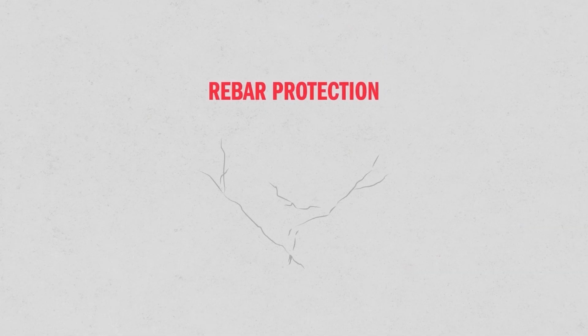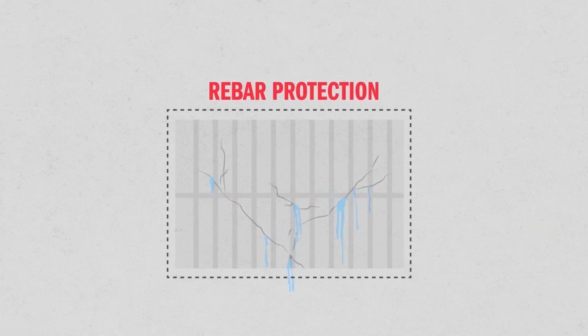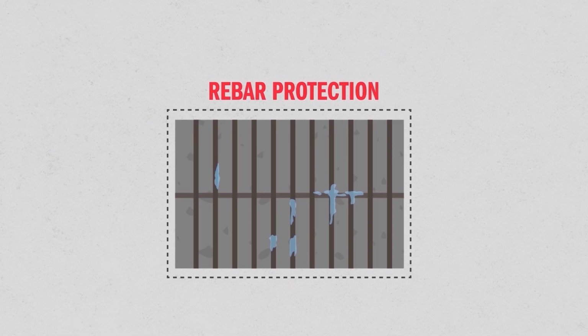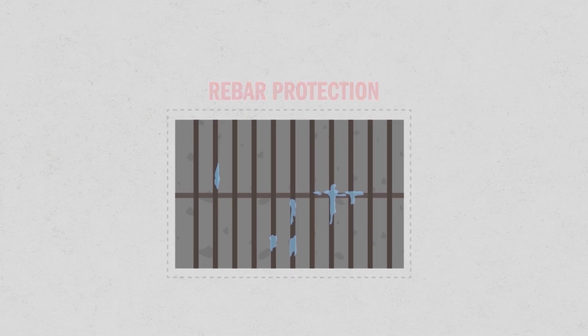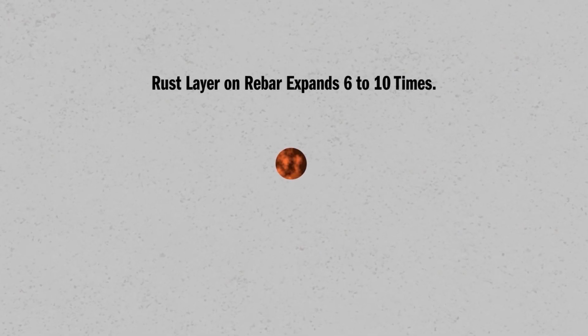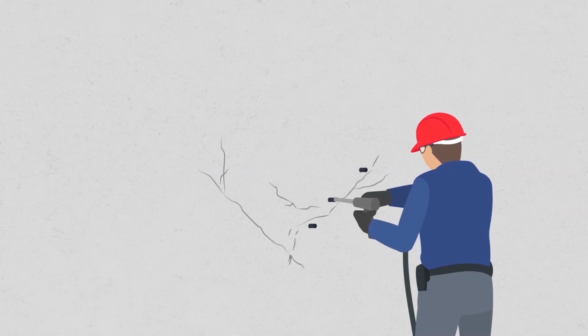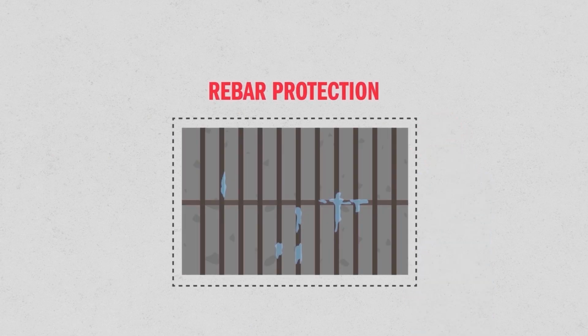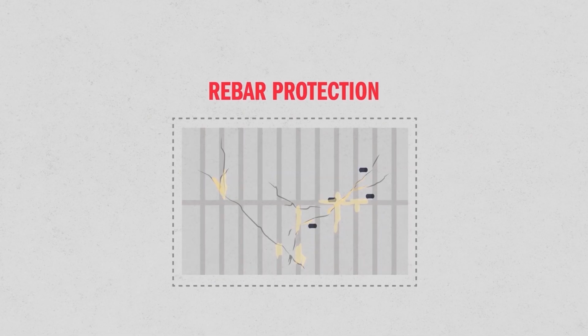Another advantage to sealing leaks with polyurethane is rebar protection. Water intrusion through concrete walls with reinforcing steel can lead to corrosion and spalling. Corroding rebar rusts and can expand 6 to 10 times the original volume of the steel. This creates internal pressure on the concrete. While concrete is very strong in compression, it has a low tensile strength, and the expanding rebar will cause it to crack. By injecting polyurethane resin under pressure, we can encapsulate rebar and slow down the rebar corrosion process. This can greatly extend the life of the structure.